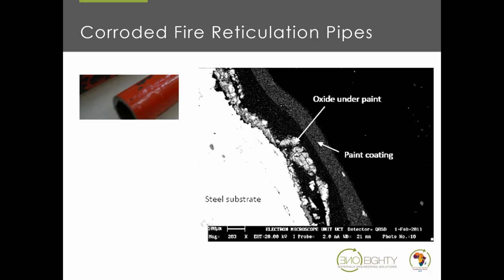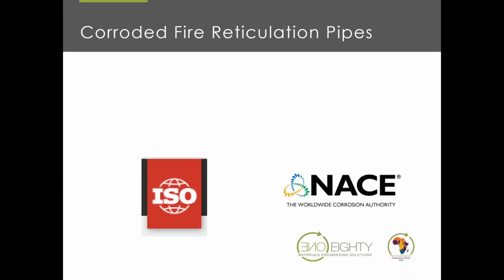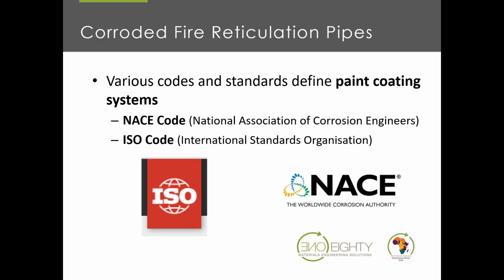All right, so to understand why or how this could have happened, I consulted with both the NACE codes and the ISO codes. The NACE code is the National Association for Corrosion Engineers, and there's a matching ISO code, International Standards Organization code. And these codes define paint coating systems and how paint coating systems work. So if you use a particular type of paint, the standard will state what surface preparation needs to be applied before the paint coating is applied to that surface, and the period of time that is allowed between the surface preparation and the application of the paint. So paint is not just paint. Paint is both the paint and the surface prep together. So it's a paint coating system.